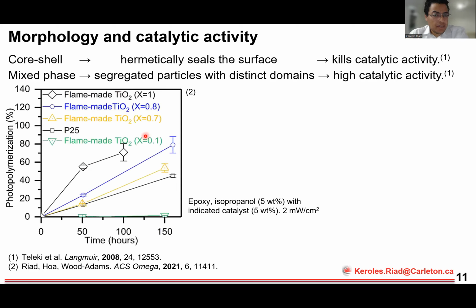Here, I compare the performance of pure titania as well as with 20% and 30% silica, so it's x equal 0.8 and 0.7, as well as x equal 0.1. And you see, even with 20 and 30% silica, the kinetics for the catalysis here is higher than P25, which, as I mentioned earlier, is the gold standard for photocatalytic activity. So clearly, the amorphous silica does not hermetically seal the surface, so the catalysis is still possible.